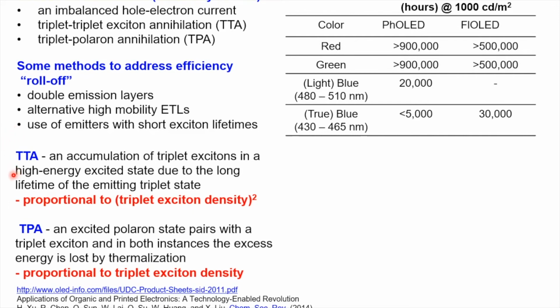Triplet-triplet annihilation essentially occurs when the triplet excitons, which are excited by applying electricity to the OLED, have a long excited state, and when they hang around for a long time, especially at high applied powers to the device, you can build up many triplets in the material, and rather than decaying radiatively, they will annihilate each other and create degradation to the molecular structure of the emitter. Triplet-polaron annihilation can also occur at high triplet exciton densities when triplets interact with charged polarons in the device.